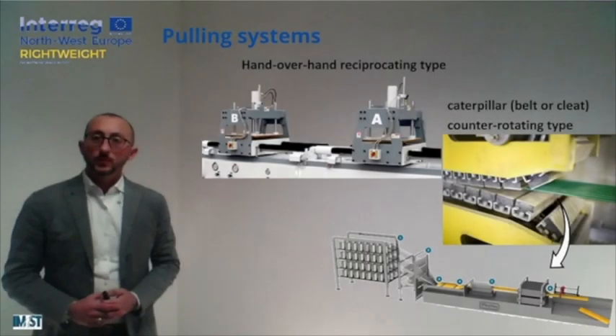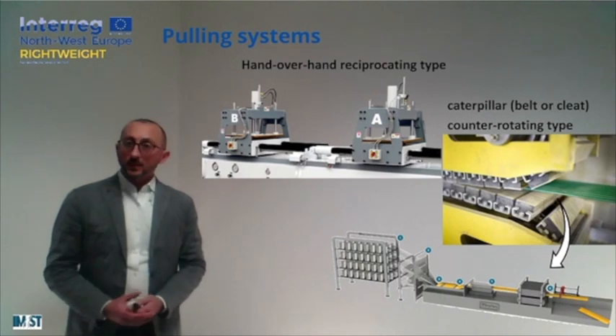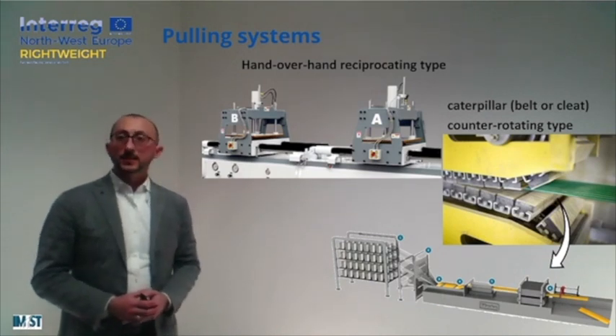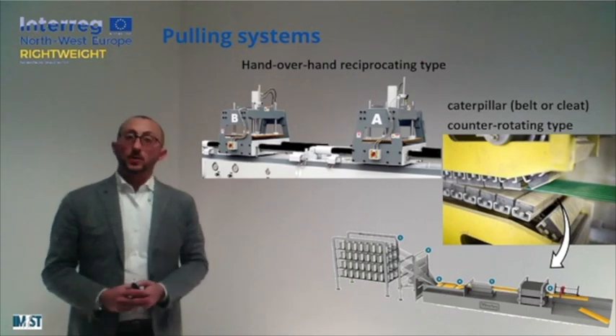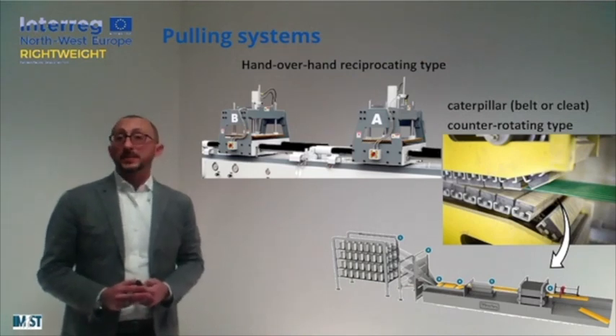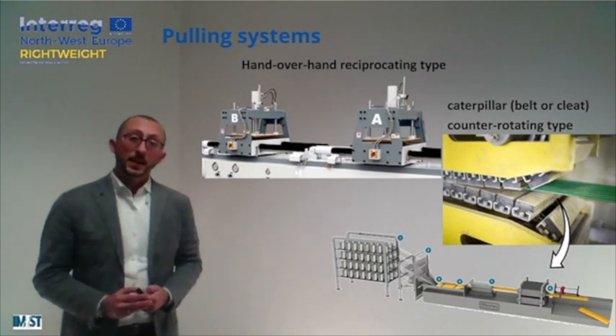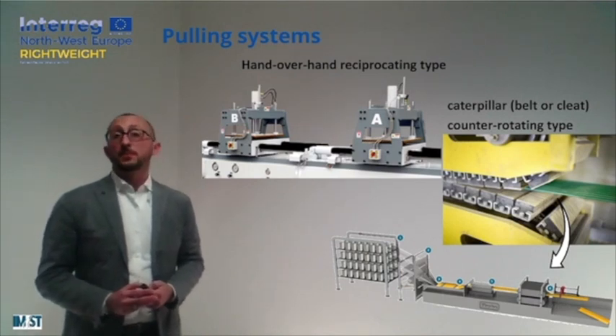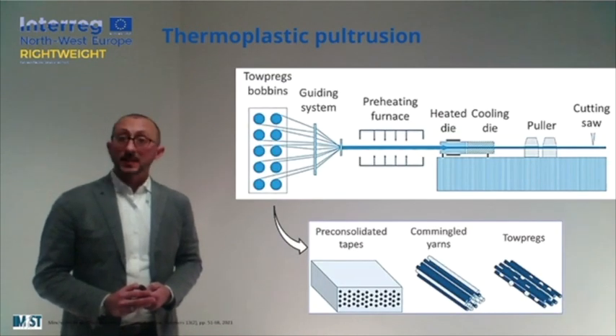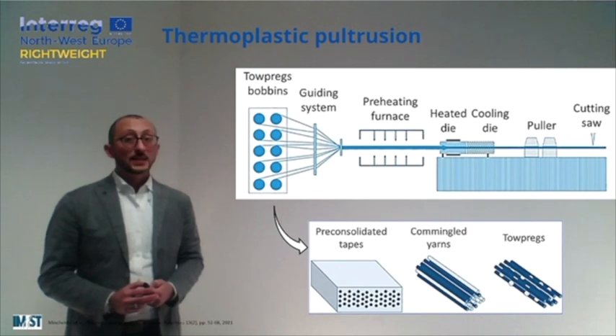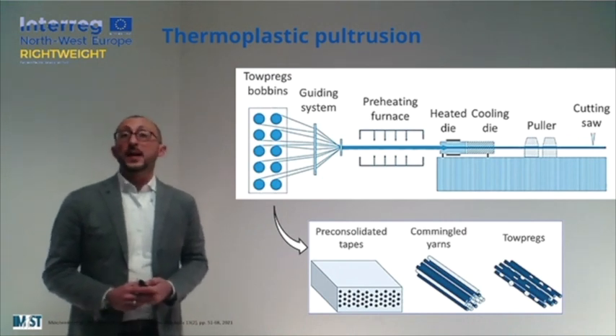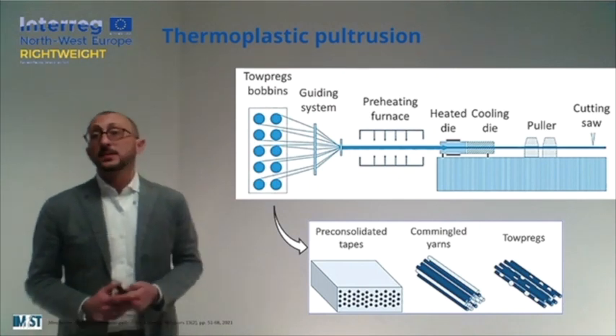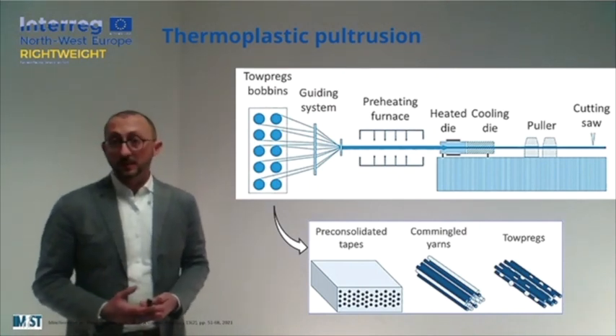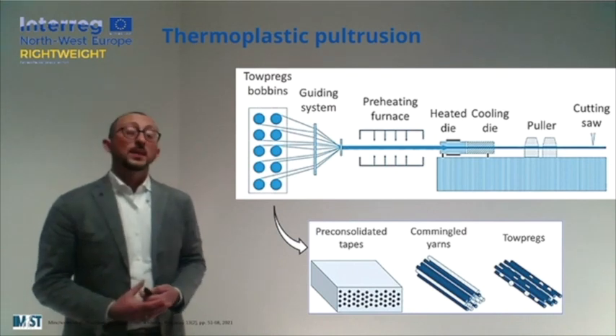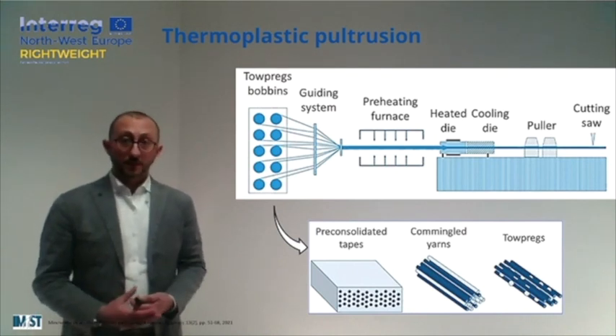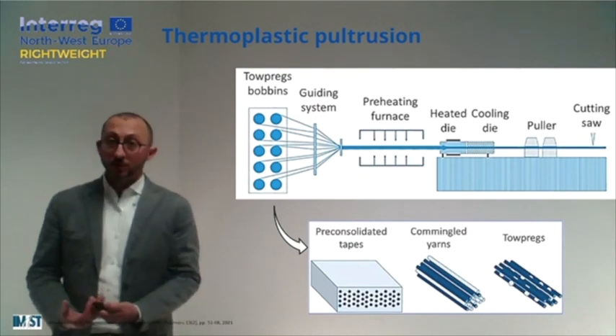The configurations that we just saw are quite common when we are processing a thermoset resin as matrix for our composite material, but some variations of the pultrusion line are necessary if our matrix material is represented by a thermoplastic resin. And this is mainly related to the fact that thermoplastic resins have a high viscosity at room temperature. They cannot be easily processed in order to have the impregnation stage.